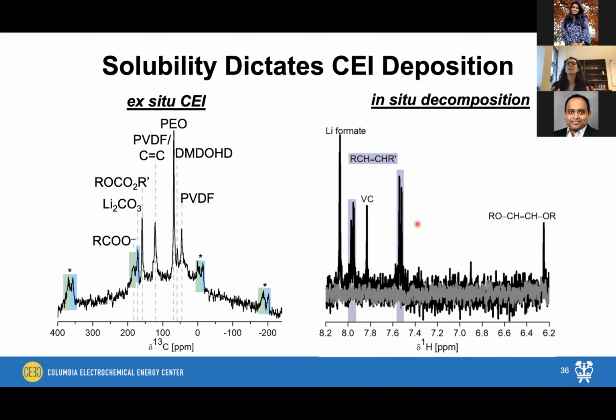But the fact that we see them in in situ proton NMR, which is primarily monitoring the soluble decomposition products, indicates that even though these vinyl products might be formed due to electrolyte oxidation at the NMC811 surface, they are soluble enough that they can detach from the particle surface and then be floating around in the electrolyte where we can actually detect them in this experiment. And because they're floating around in the electrolyte, they don't really care where they deposit onto. So they're depositing sort of indiscriminately onto the outer CEI of the NMC811 particles.